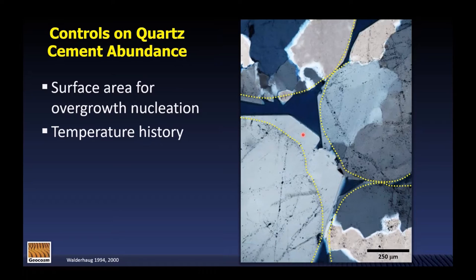The other problem that people have focused on quite a bit is the transport mechanisms that would take that dissolved silica from where it came into solution to where it would ultimately precipitate out as an overgrowth. People looked a lot at advection, that is the movement of silica-bearing fluids, or molecular diffusion. Now what Olav realized, in doing exhaustive fluid inclusion analysis of quartz overgrowth, and also doing basic modeling to get temperature histories, was that the rate at which these quartz crystals grow in the subsurface is incredibly slow.